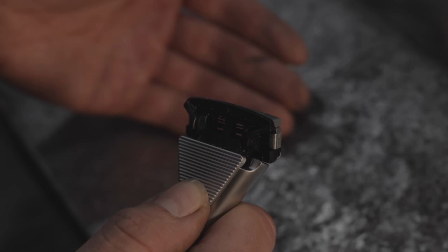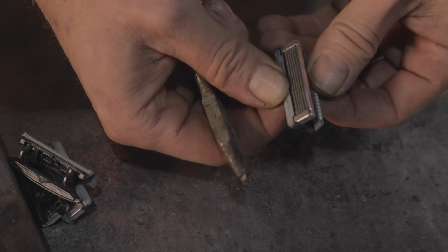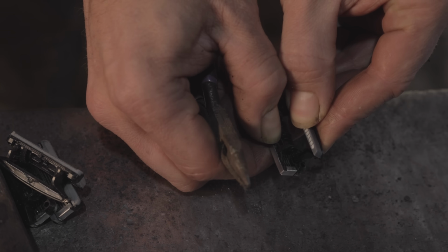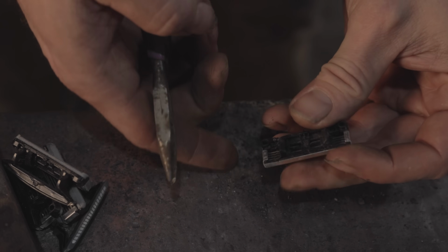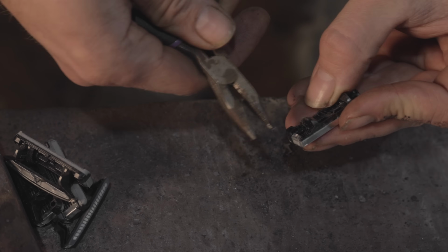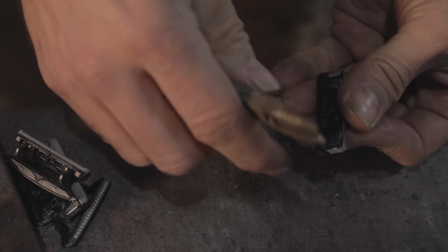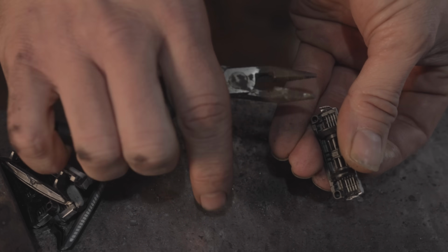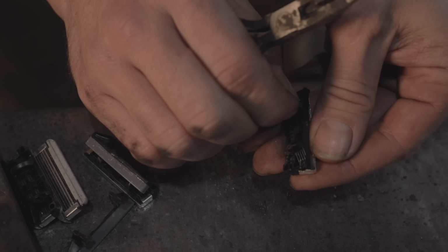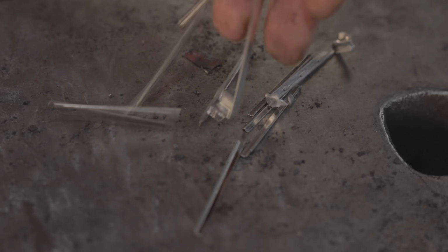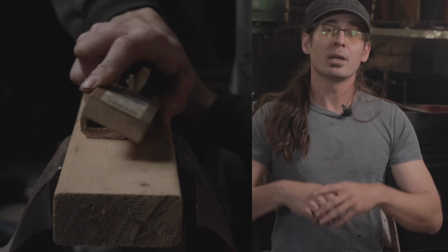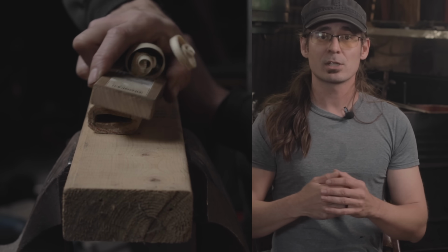In the video we show the commercial level putting in the razor blades with the plastic. We didn't do it like that. What we did, we took out the steel, put it in the crucible, mixed in a little bit of iron in there just to help with the forge welding down the line and to dilute some of the chrome alloys just a tiny bit. Add a little bit of vanadium-containing steel just to keep the mixture really nice, because you want vanadium to reduce grain growth in your final product. So we made our own homebrew based on the razor blades.